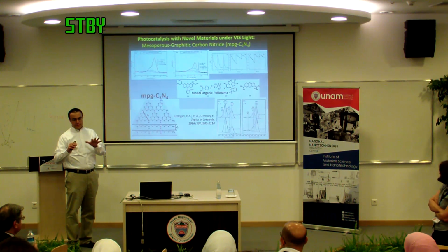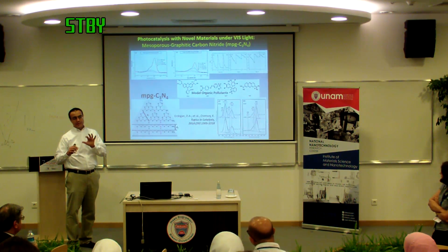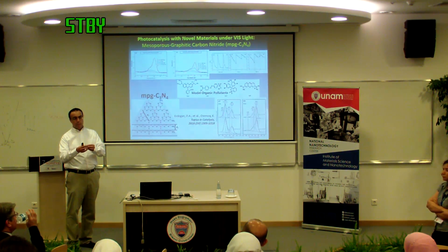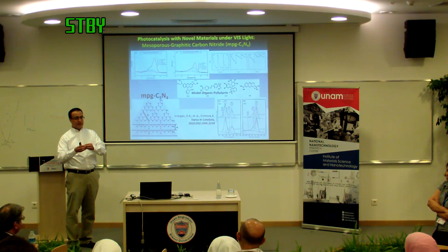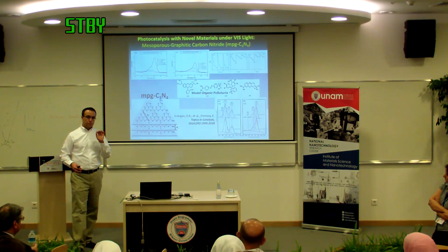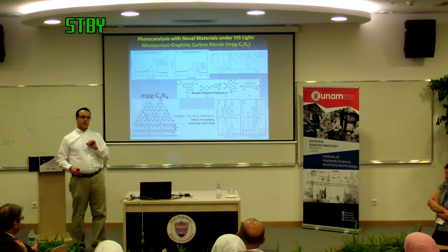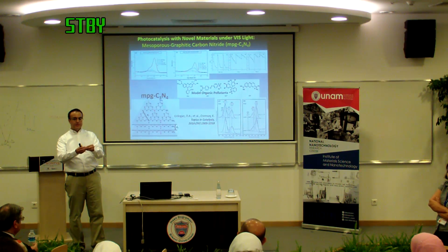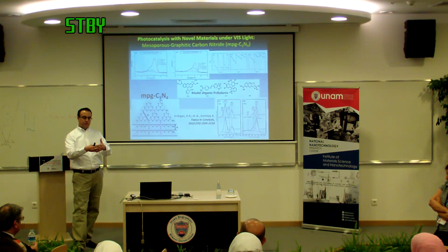We prepare them in a special way so that we don't want them to be crystalline. So you still have barium oxide domains, but they're amorphous, small particles, not well-defined. XRD patterns are completely amorphous. In that particular case, you prevent the formation of crystallites. Because with high temperature and all that, those crystallites eventually thermodynamically get together and mix. But if you can limit the diffusion by mixing it almost like a glass, a ternary glass of mixed oxides, you can prevent the diffusion of cations, and then you can limit crystal growth.